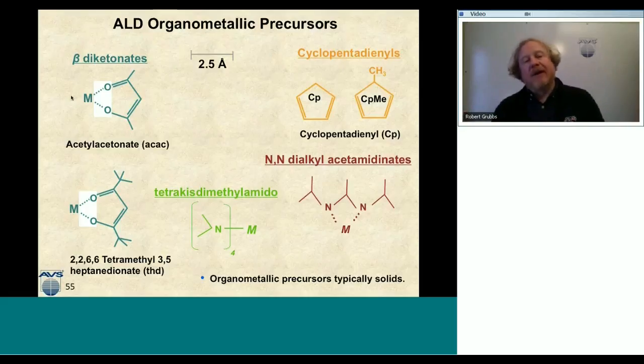An even larger molecule in the beta diketonates is this 2,2,6,6-tetramethyl-3,5-heptanedionate. And that's also described in the literature as demarcated as THD. So you might see a molecule that has a metal atom with THD. And what they're referring to is this very large, very exotic molecule right here. Again, it's a large molecule, has a lot of real estate, and is typically used to put down more exotic metal atoms on the periodic table.